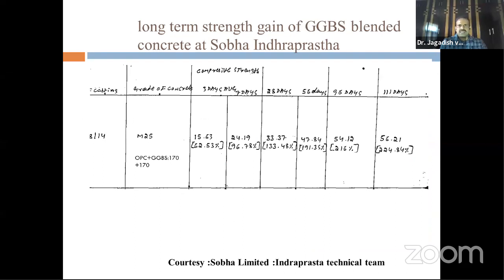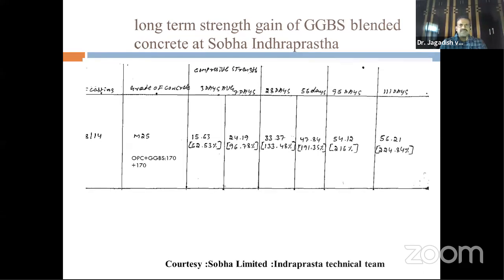Yeah, this is the same Sobha Presta. This is the actual sheet of long-term strength gain. At 111 days, it is almost like 224% strength gain from 28 days. Okay, so at 28 days what they got is 33 MPa, and then at 111 days it is like 56 MPa, wherein they've used 170 cement and then 170 GGBS for M25 grade of concrete. This is for the Sobha Presta project.